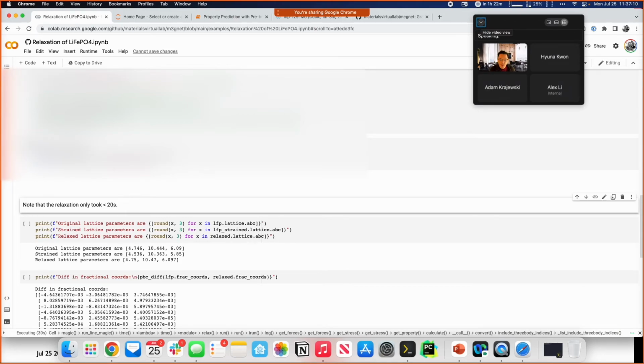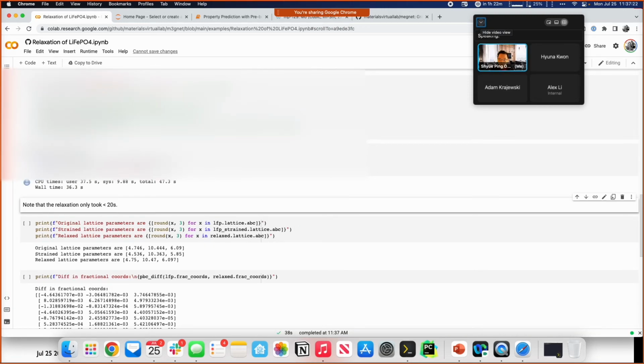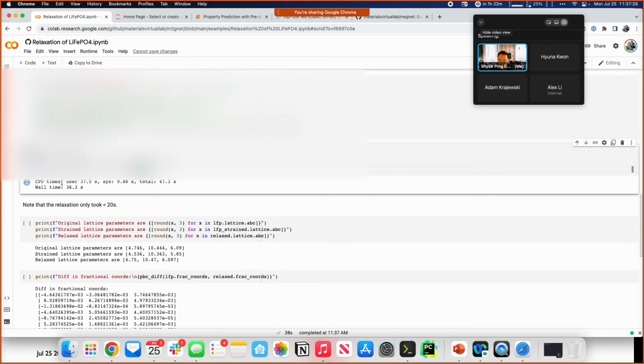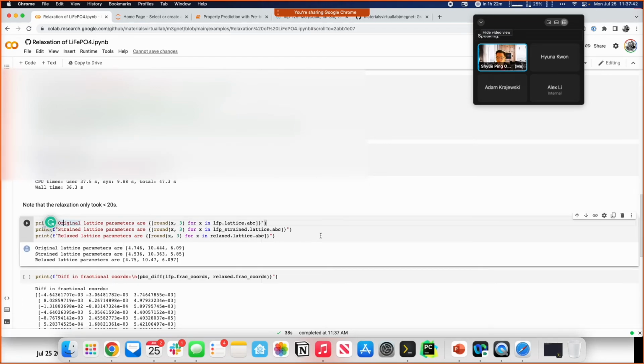Most of this step is actually involved in downloading the potential and initializing. So if you are using this for much bigger crystal structures, a lot of crystal structures all at once, it's not going to take this long. Now, here it says that the wall time is 36 seconds. So it does take a bit longer than if you're running on a local machine. If you run on a local machine, you should be able to get it within less than 20 seconds. Okay, so definitely much quicker than your standard DFT calculations.